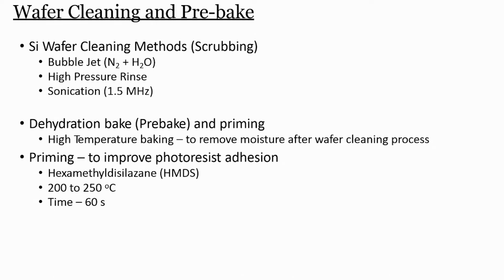So, when you talk about wafer cleaning and pre-baking, silicon wafer cleaning methods are scrubbing, air bubble jet, high pressure rinse, sonication at 1.5 megahertz, followed by dehydration or pre-bake and priming, high temperature baking to remove moisture, as we have discussed earlier. After the wafer cleaning process, we then have to use a primer coating. This primer coating is to improve the adhesion of photoresist, and this primer is hexamethyldisilazane, which is HMDS in short, and the temperature can be 125 and above. Some people also use 200 to 250 degrees centigrade for 1 minute on a hot plate. This is to improve the adhesion, right.